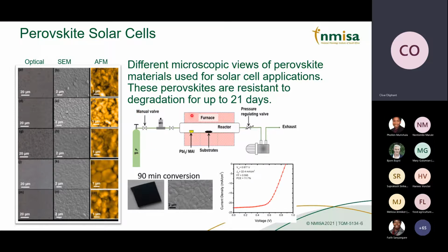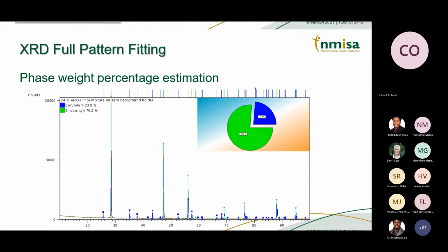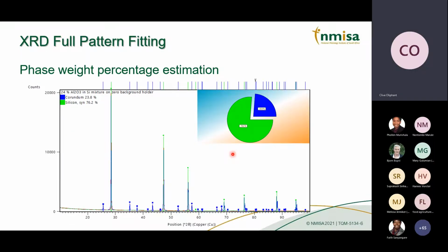So NMISA is involved in some projects from the start to try and always keep up to date with recent developments. We also have X-ray diffraction, as I have mentioned, and this is one of the techniques that, even though it's been around for a very long time, is still useful for these advanced materials where we can estimate how much is crystalline, and you can also get the amorphous fraction. But here we have a 24% mixture on a zero background holder, and from fitting the complete profile and doing this Rietveld refinement against standards, with calibrated equipment, we got quite close. This is just a typical example showcasing how XRD can be a very good, insightful technique if we use it correctly.